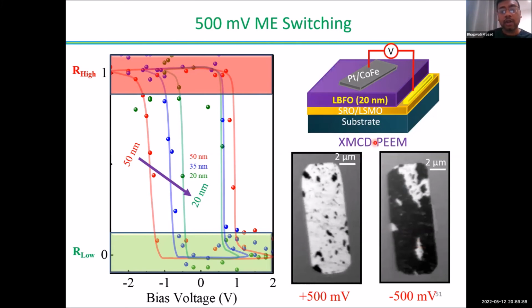Okay, so we also demonstrated this with the PEEM. Here we have put thin cobalt iron on top of this 20 nanometer LBFO, and then we apply the electric field, plus 500 millivolt, and we did the XMCD PEEM, and then we apply minus 500 millivolt. Then you can see that we could switch almost 70 to 80% of this ferromagnetic domain by applying the electric field across this multiferroic LBFO.